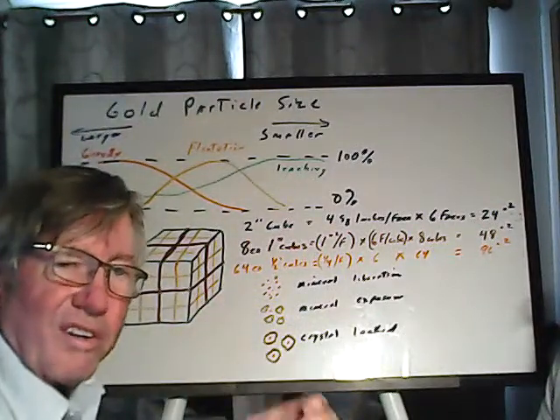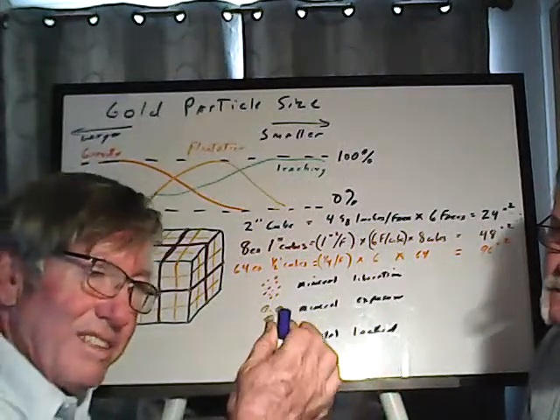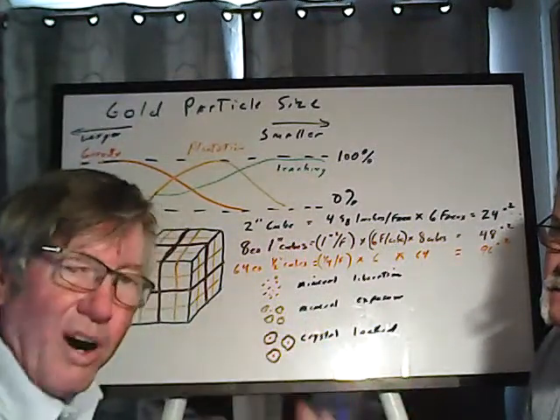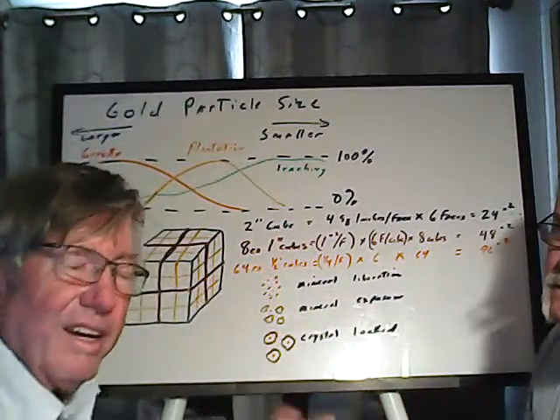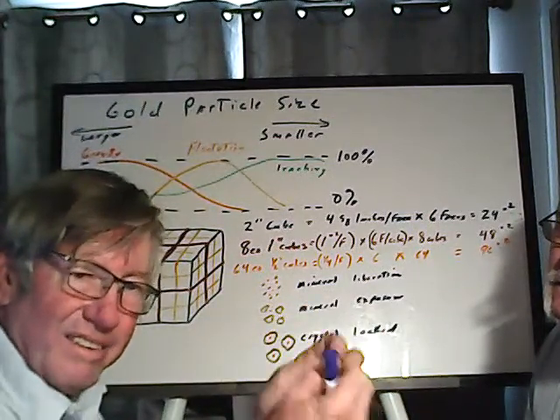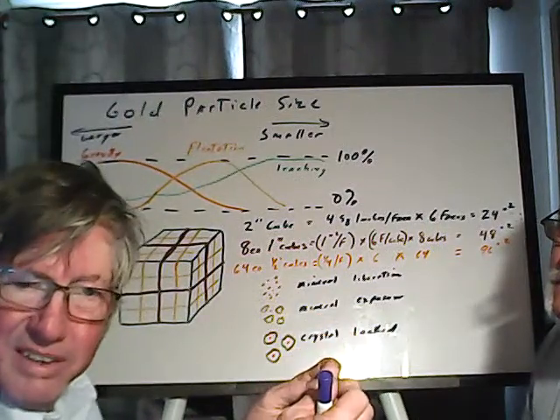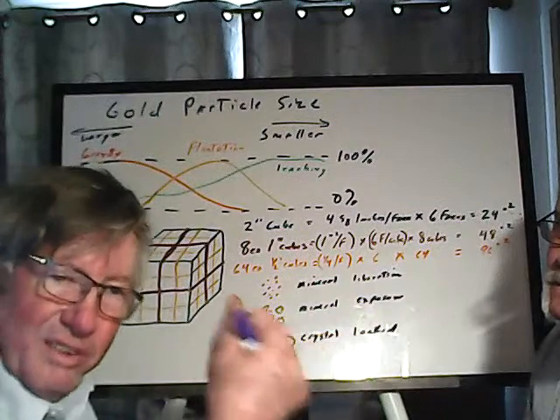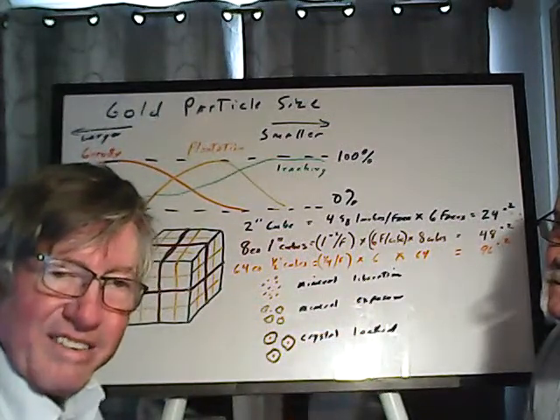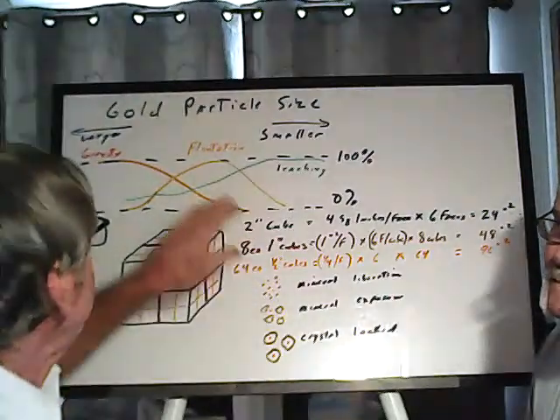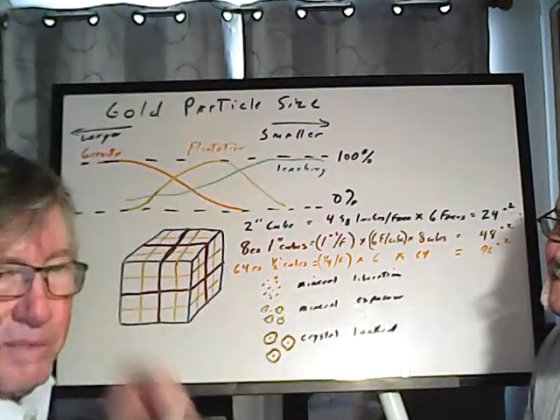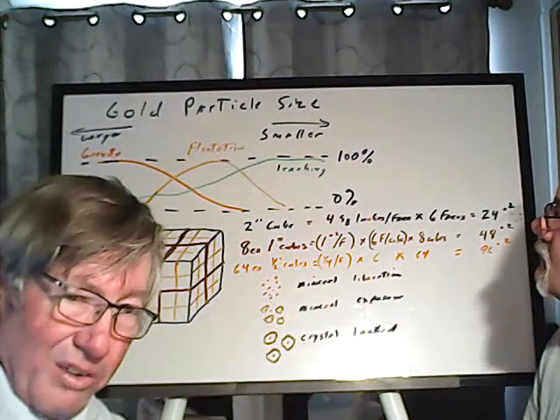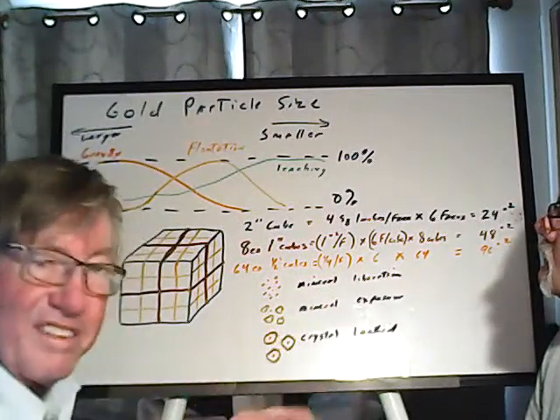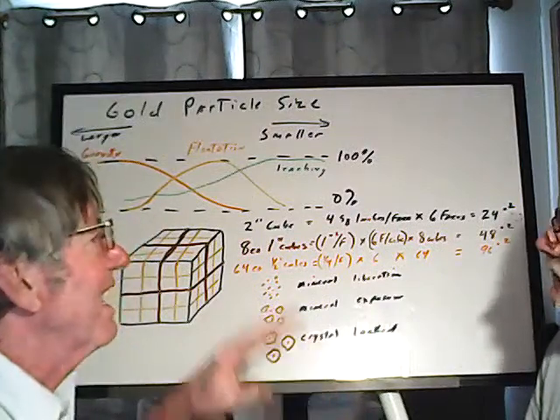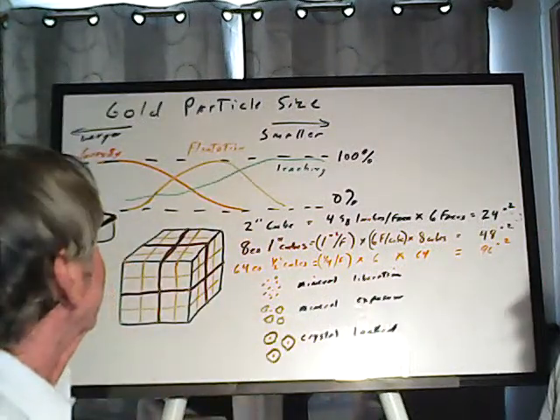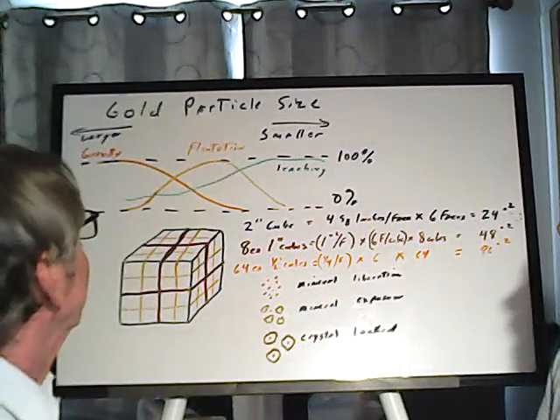In order for it to work, the gold particle or the mineral particles have to be separate from the rock particles. You have to crush rock to get it to that point. Hard rock, the valuable mineral is not separate from the other minerals. You have to crush it and separate it if you need it separate. And flotation works kind of in the mid-range. It doesn't work for the very smallest gold, and it won't work for the very biggest gold. It's not going to float those nuggets, okay? It's basically sand size to powder size in there is where you can get your recoveries.